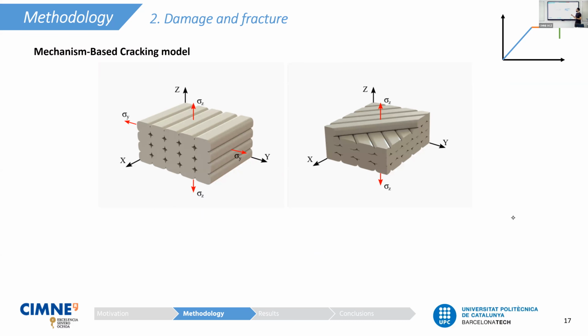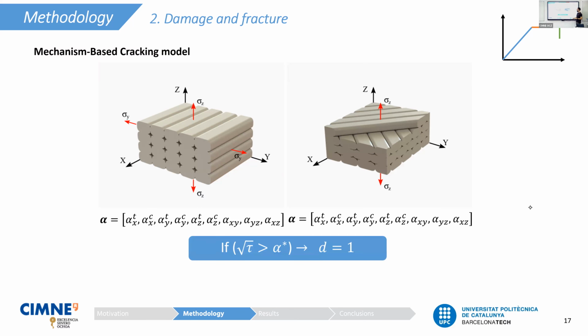And finally, once we have established the stiffness degradation, we have to model the breaking, the fracture of the material. In order to model this, we have developed a mechanism-based cracking model. In this cracking model, basically, we establish that if the square root of the tau value that we have computed, or the square root of the stress factor that we have computed, is higher than a certain value that we call alpha star, we set our damage equal to 1, meaning that we fully break the material.